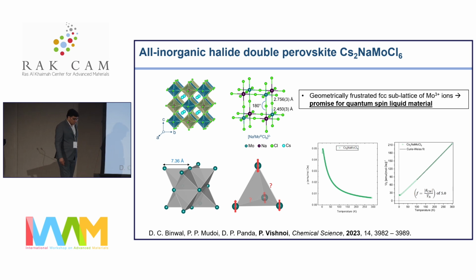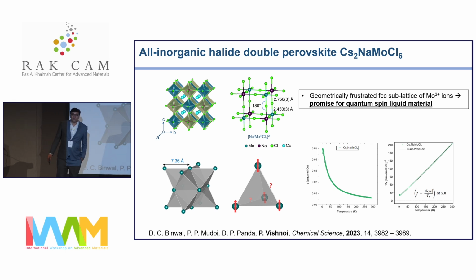Now, this is one of the structure types which possibly can give quantum spin liquid material, because these ions at the corners of a tetrahedron cannot magnetically find a single ground state, particularly when we talk about antiferromagnetic coupling, because they cannot cancel each other. And such a situation often leads to a quantum spin liquid, meaning they don't antiferromagnetically couple even at very low temperature.